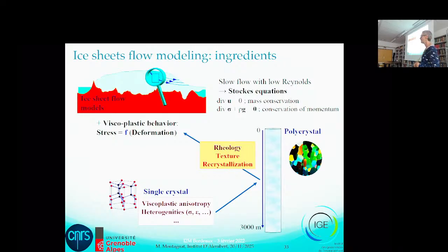But right now I'm working with some colleagues in Géosciences Montpellier, Andrea Tommasi, for those who know her, and we are working on magnesium because we want an analog of olivine. So olivine is not hexagonal, it's orthorhombic, but it's also highly anisotropic, and it behaves a little bit the same, so that in shear it creates some very strong single maximum, it has a lot of dynamic recrystallization mechanisms and so on. We have been working together for more than 10 years, I think, with Andrea, because ice can be considered as an analog for olivine, because we can do experiments as we can for ice.